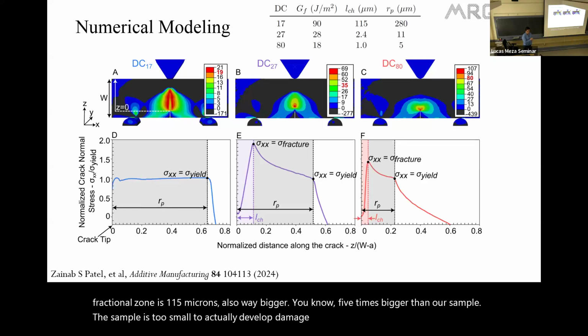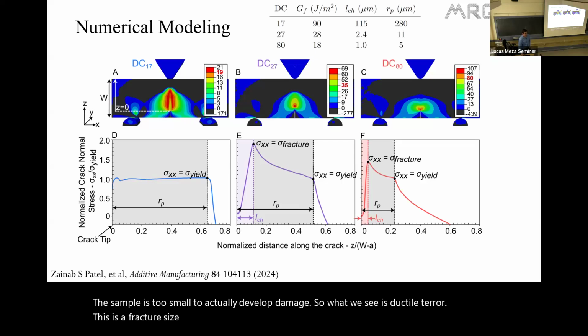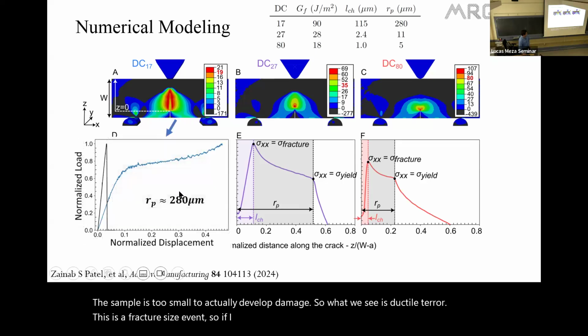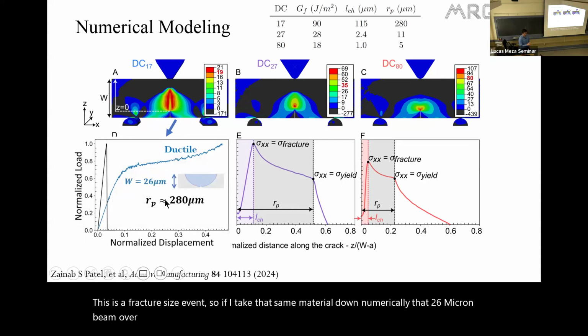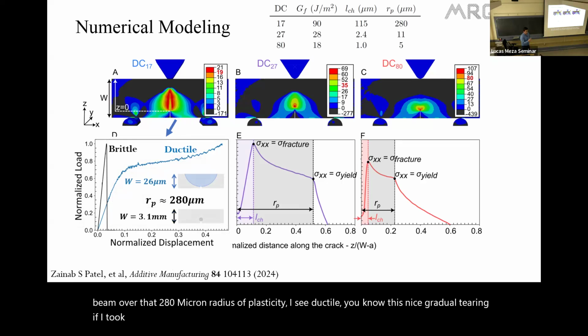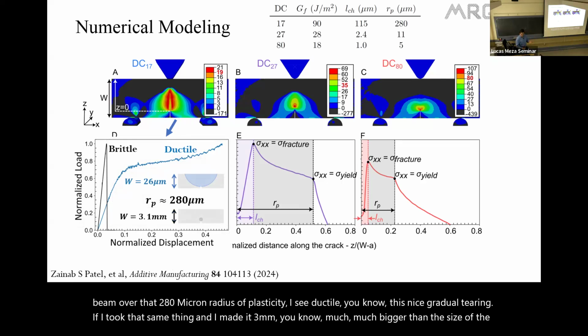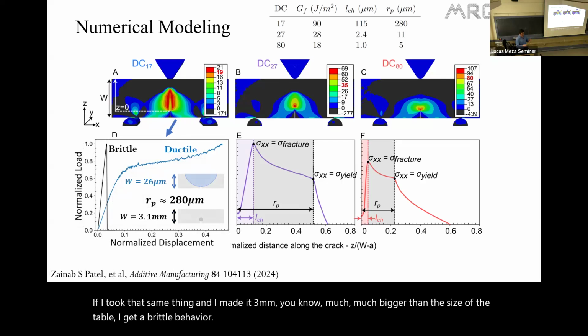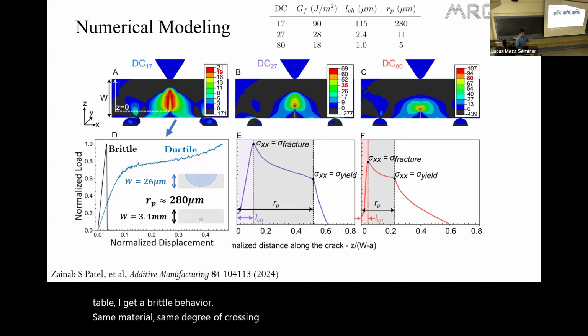So what we see is ductile tearing. This is a fracture size effect. So if I take that same material now numerically, that 26 micron beam with that 280 micron radius of plasticity, I see ductility, this nice gradual tearing. If I took that same thing and I made it 3 millimeters, much, much bigger than the size of the sample, I get a brittle behavior. Same material, same degree of cross-linking in this case, now size affected.